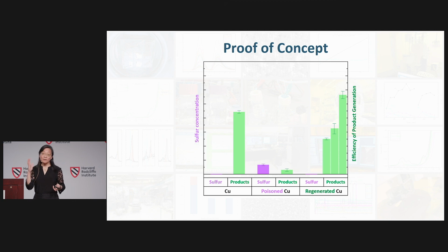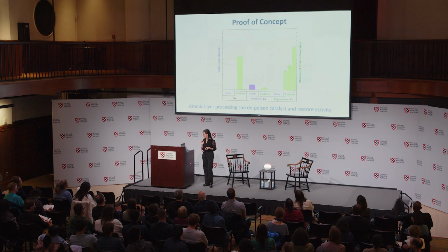The most interesting one is we have one set of data where we have significant improvement compared to our clean surface. Why? If we remove the sulfur completely, shouldn't we just restore the property? Why are we changing it? Why are we making it better? It turns out that in that particular condition, we use a slightly more aggressive plasma. And that particular plasma, when we look at the surface of the copper using a scanning electron microscope and atomic force microscope, we see that the microstructure and the morphology of the copper has changed. In catalytic literature, that is usually a cause for increased efficiency in the product formation. So clearly, there's room for improvement so that we can fully understand these processes, but the proof of concept is done. We have shown that the atomic layer etching process can depoison the catalyst and restore the activity.